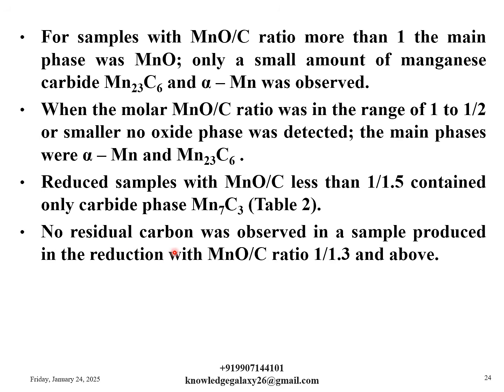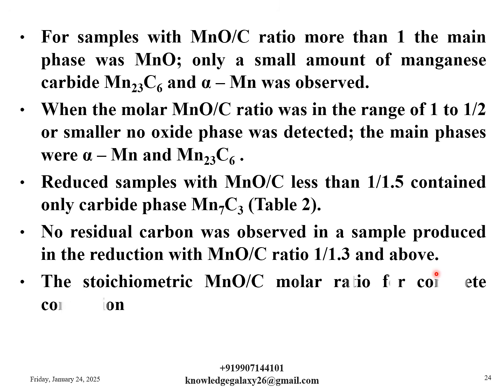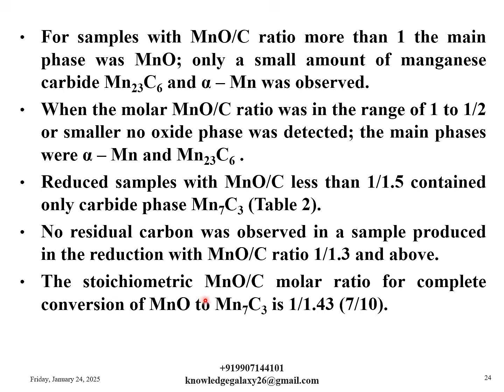No residual carbon was observed in a sample produced in the reduction with MnO by C ratio 1 by 1.3 and above. The stoichiometric MnO by C molar ratio for complete conversion of MnO to Mn7C3 is 1 by 1.43, that is 7 by 10.